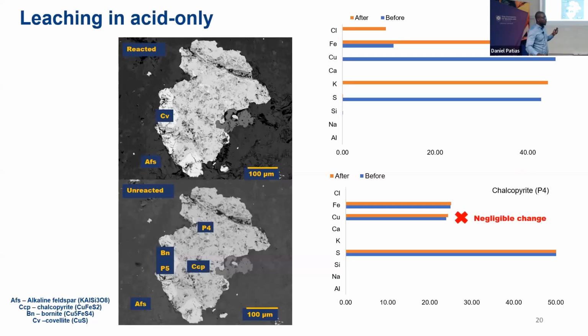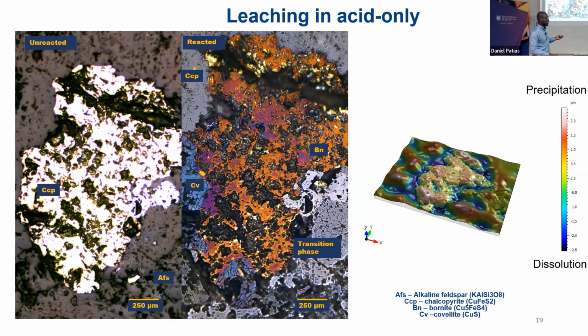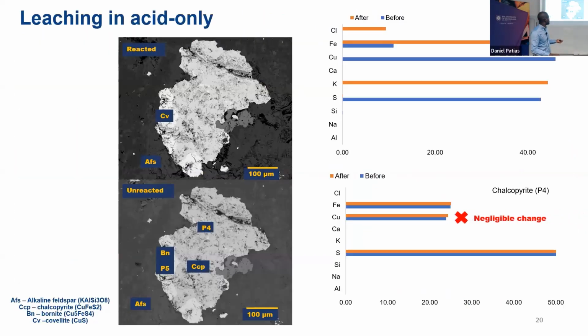Using the same points of interest, giving it to the EPMA to understand the chemistry, we realized there's actually negligible copper, as we saw in this image. There's apparently no copper dissolved. It's rather transforming, but it's not dissolving. So this is what we had for leaching in only acid.